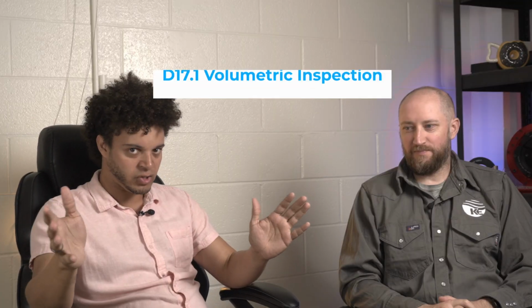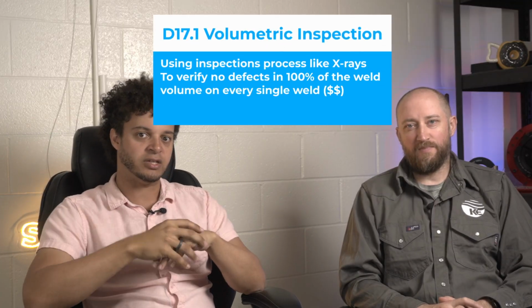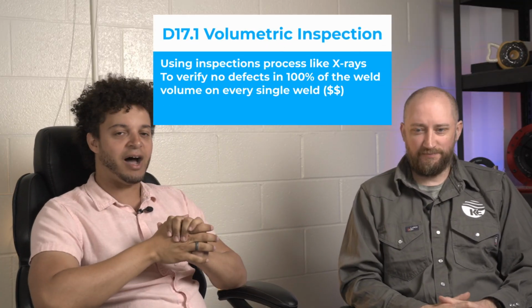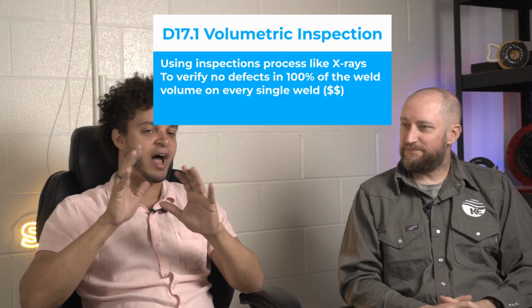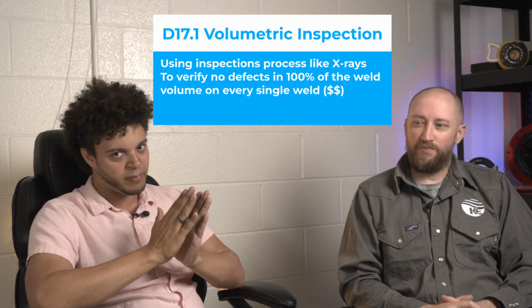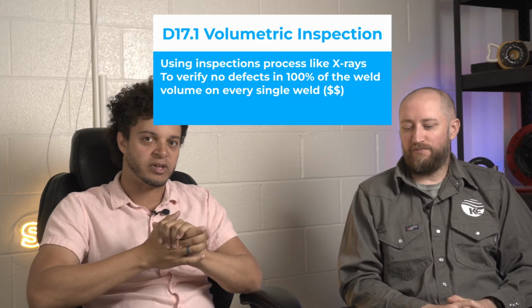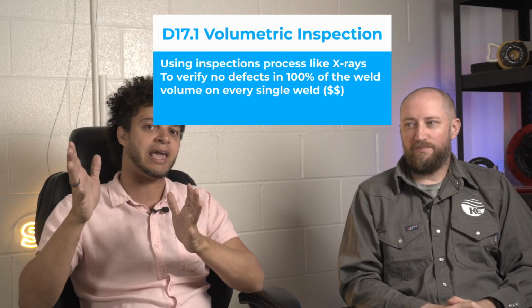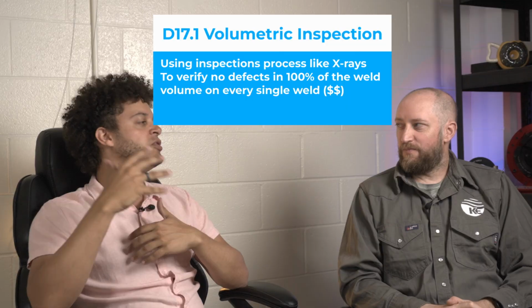The reason I say it's a high quality code is that it basically assumes and demands 100% volumetric inspection for every single piece if you're doing Class A. Class C, not the case, but Class A, 100% volumetric inspection. So this gets you away from the shenanigans that in other codes are like, hey, in D1.1, you don't have to do this.